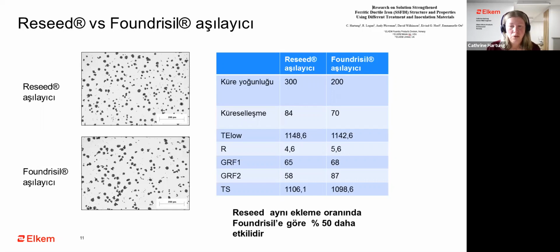So for ductile iron, it's common to look at nodule density and nodularity along with the thermal analysis. So we don't look at chill levels, although we could do that too, but it's not primarily how you measure the nucleation performance. So in this case here, we see that the Reseed is providing a higher nodule density and nodularity compared to Foundrisil. In this case, the iron in question was a solution strengthened ferritic ductile iron of the type 610. And the main thermal analysis parameters are also better with Reseed than Foundrisil in this case.